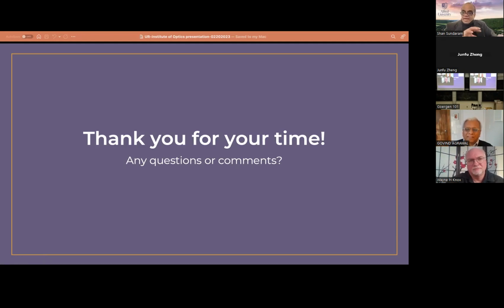Yes, you are right. In the visible range for silicate glasses, it fits better. So the Naftaly group I mentioned to you measured commercial silicate glasses like crown and quartz glasses, and they plotted terahertz refractive index as a function of visible refractive index for various values. They showed there is a linearity, and the linearity is tied to how much polymerization or depolymerization, how much I'm changing the structure using alkali. So they tried to simplify for silicate glasses. If I change my modifier, my visible refractive index changes linearly with my terahertz. So they did provide that, but no one has looked into whether any of this linearity works for other families.